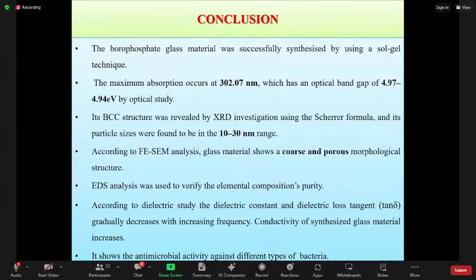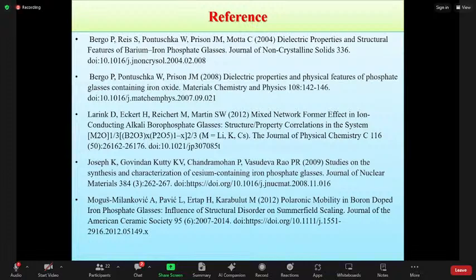The EDS analysis was used for elemental detection. Then, according to the dielectric study, the dielectric constant and dielectric loss tangent gradually decrease with increasing frequency. That means conductivity is checked by the dielectric study. It shows antimicrobial activity against different types of bacteria. These are some references.